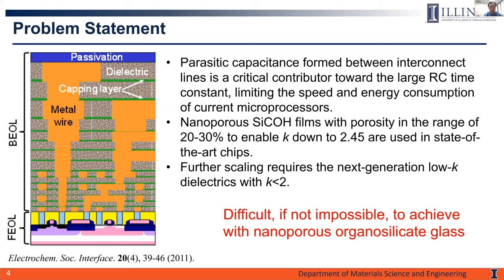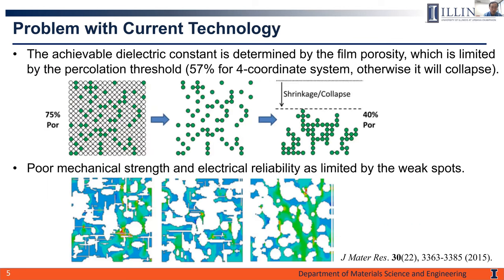However, to support the further scaling, which is in terms of the performance of this dielectric material, we need the K value to become smaller than 2. And this is a very challenging target. It will be very difficult, if not impossible, to achieve with current nanoporous organosilicate glass dielectrics for several reasons. Well, so first of all, current low-k dielectrics, we have this random pore structure generated by the release of porogen species under the thermal treatment during the chemical vapor deposition process.